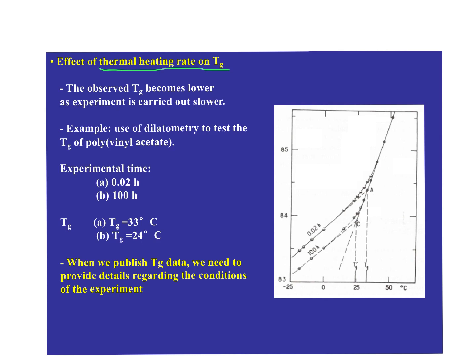So if you heat at 1 degree C a minute, maybe it doesn't make a big difference. But if I heat at 10 degrees or 50 degrees a minute, which is kind of crazy, the furnace may say, oh, I'm at 100 degrees, and the polymer may say, hey, I'm only here at 40. I haven't gotten anywhere near 100 because it's such a lousy thermal conductor. And so that can cause observed artifacts in the systems that might make you think that the glass transition is something other than what you read in the book, for example.